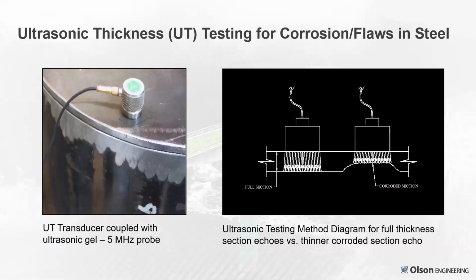So the next thing I'm going to talk about is ultrasonic thickness. This is for testing for corrosion flaws in steel. You've got a transducer coupled with ultrasonic gel shown here on steel. Basically, if you have a corroded section, you will get a shallower, thinner echo. It is not as thick versus a full section echo.